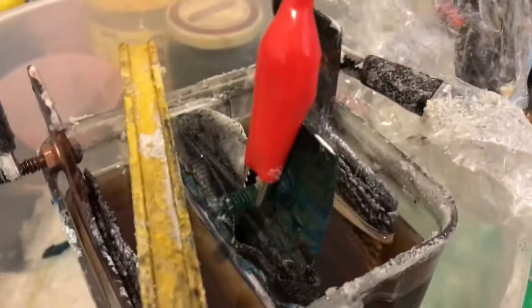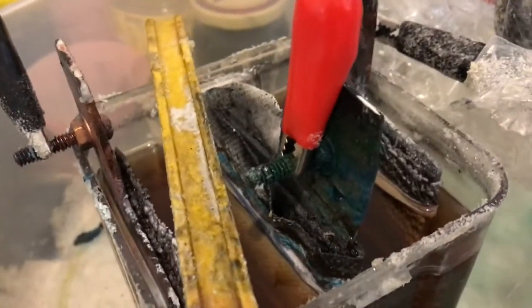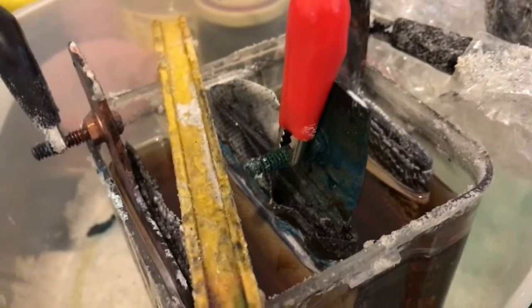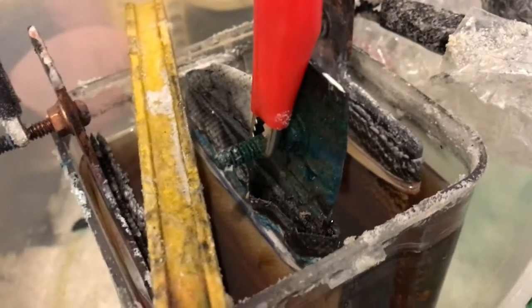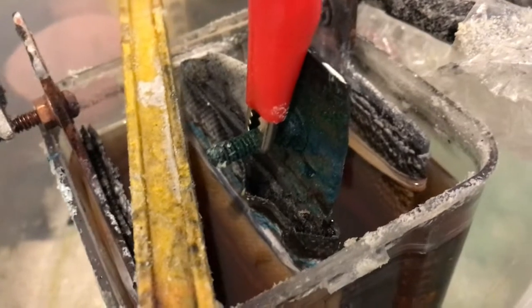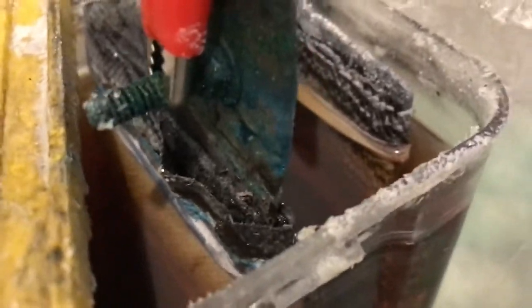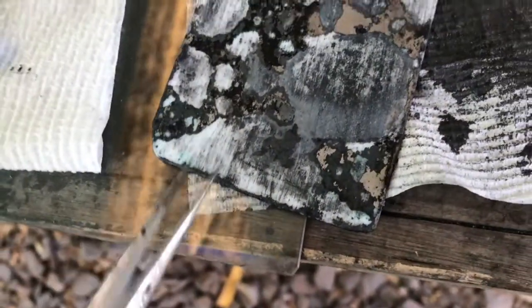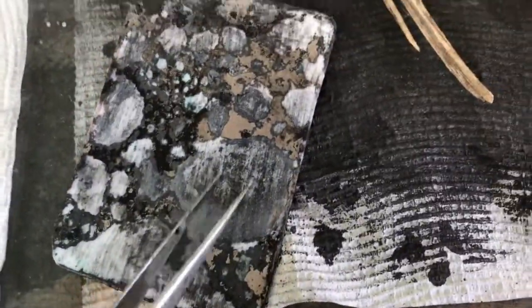I'm going to try a mild steel plate setup. It will save using ink and also copper plating. You won't have to do it, you'll just have to nickel plate completely. So I'll glove up, get that stripped down, and then we'll check this plate out properly. Okay, we have multiple failures actually on the positive plate of the plating. So we're back to bare plastic through here, up here, through here and everywhere else. And that's on both sides.